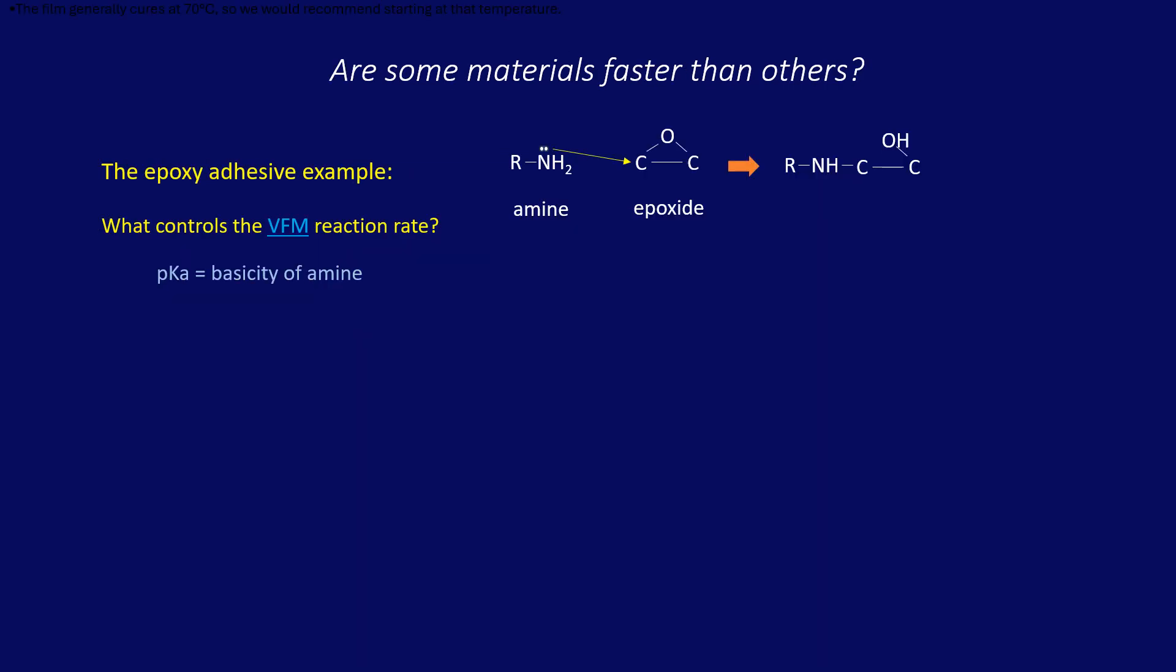Do some chemicals react faster than others in microwaves? Once again, we look at the example of the epoxy cure, because it's used very often in many applications. Not surprisingly, stronger amines will increase the speed of reaction. Total polarizability should be better for microwaves to spin the molecules. Rotational entropy usually only affects chemical reactivity by a few percent.